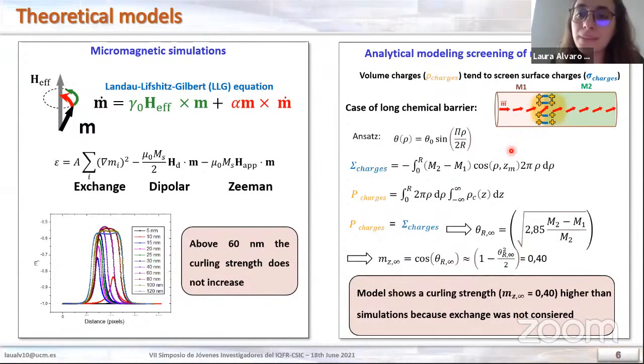And then to understand it better, we performed an analytical model where we see that the curling occurs to have volume charges that can screen the surface charges at the chemical barriers. So then when we model a complete screen of volume and surface charges, we observe again that maximum curling is not possible due to the cost in exchange energy.